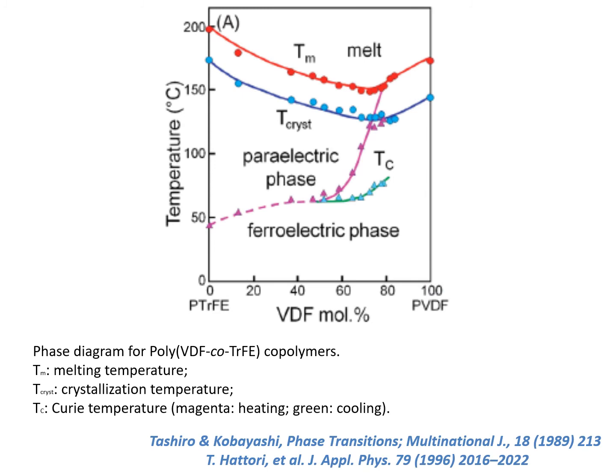So this was also revisited by Tashiro and Kobayashi. This is a very nice paper here in 1989, and they even revisited that in 2006. And the profile of melting temperature does not change from what was observed by Yagi and Tatemoto on the slide before, while the crystallization temperature is also ranging more or less in the same tendency, and the ferro-paraelectric Curie temperature changes a little bit according to whether you cool it or melt it. So you can have a non-significant amount of difference between the processes you use in order to have different Curie temperatures.